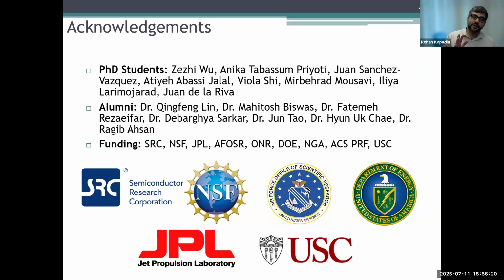The thing about SiOx, where x is less than 2, is that if you heat it up, it breaks apart and you get silicon and SiO2. So what ends up happening is you can get a source of silicon doping from the silicon in the capping layer. That's where we see this background doping concentration from, and that's actually the reason for the temperature dependence that I showed as well.